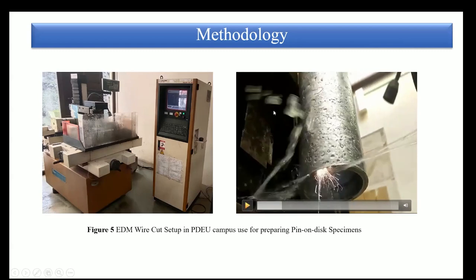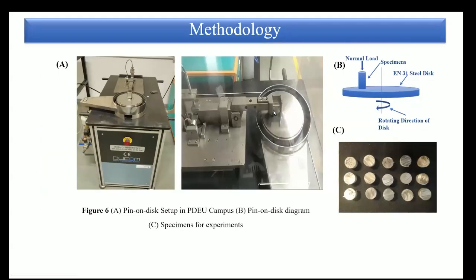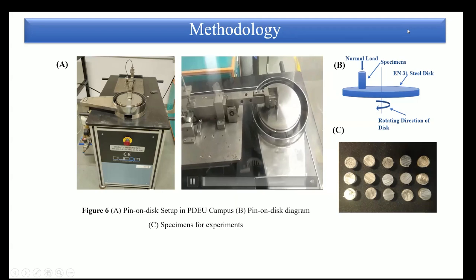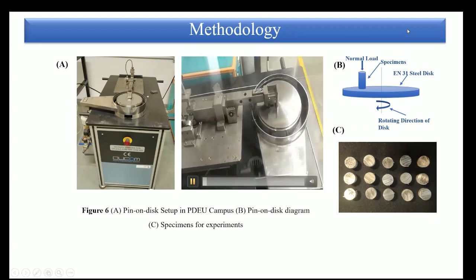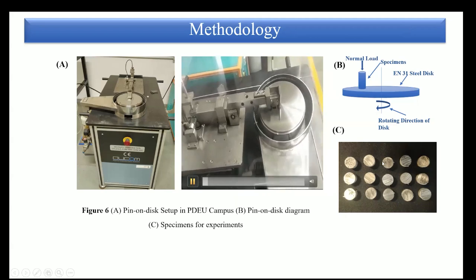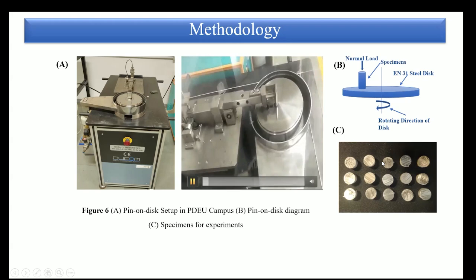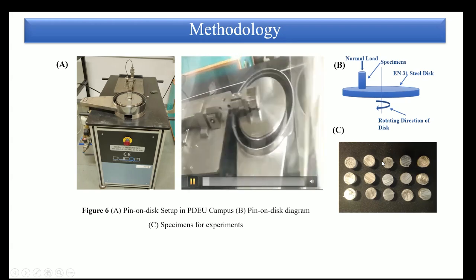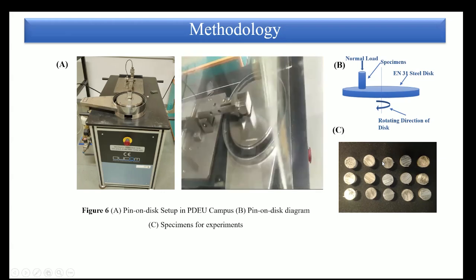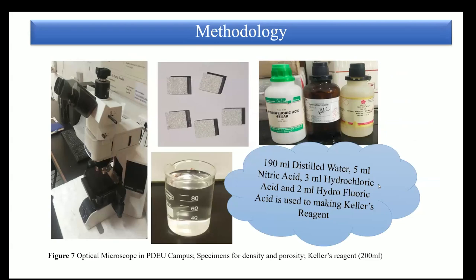This is the stir casting parameter. We choose these parameters for our casting process and our quasi-isotropic composite. And these are the pin on disc parameters and factors. In this research, we choose three factors: normal load, sliding speed, and temperature. For each we choose an upper level and a lower level: 10 and 40 for normal load, 0.5 and 2 for sliding speed, and 50 and 200 degrees Celsius for temperature. And using the Minitab software, we choose our middle points: 25, 1.25, and 125.